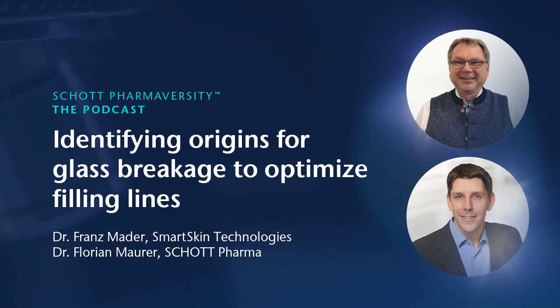So what actually happens is that the glass gets damaged and then carries these damages along the fill and finish process until application of the failure-inducing mechanical load. So to tackle glass breakage issues, it is reasonable to search for and reveal the damaging mechanisms on a line. And this is typically not where you find the shards. Okay, I understand. So really not so trivial.